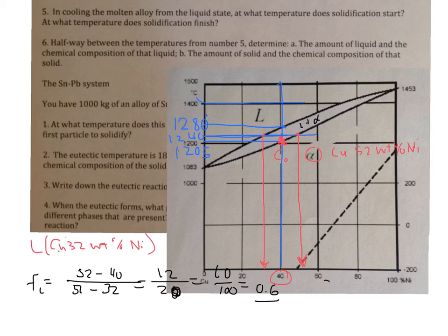And what that means is the fraction of the solid, alpha, is 1 minus the fraction of the liquid, or 0.4. I'm doing this in my head. I just substitute this fraction of the liquid here. The fraction of the alpha is 0.4.